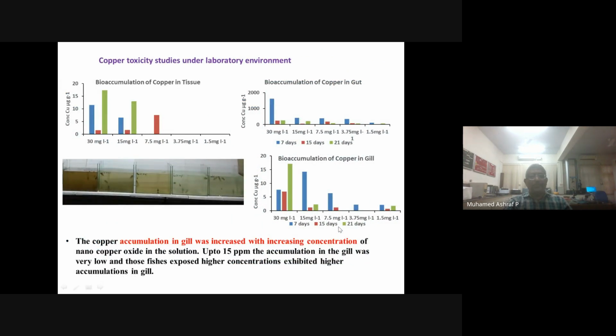Then, in the same toxicity studies we carried out in our lab, we found that bioaccumulation of copper was higher at higher initial concentrations, which is natural. But you cannot say that it is not accumulating much at the lower concentration.